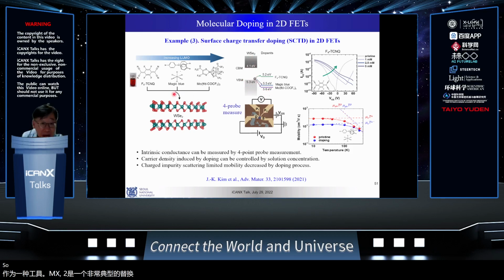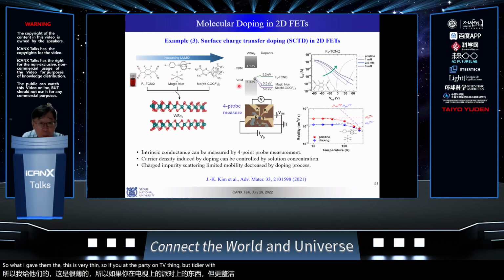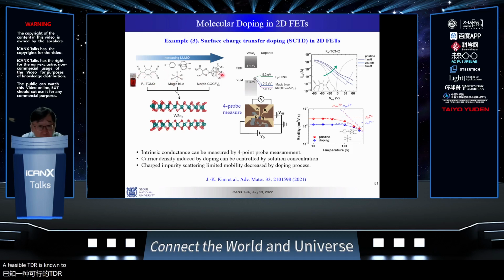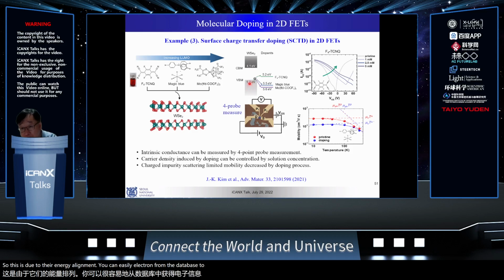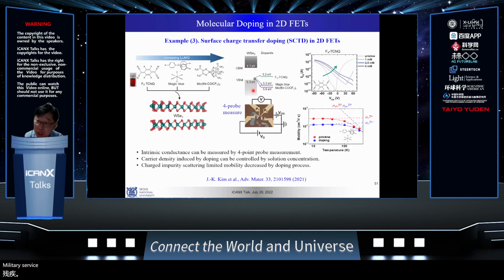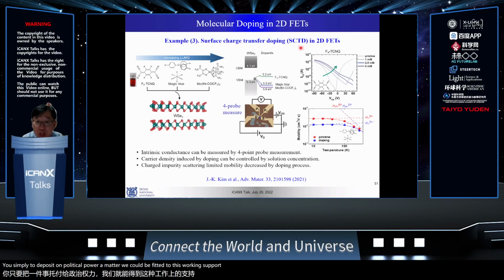So one idea is that this is very thin. If you deposit on the very thin material some molecule which has charge transfer properties, and this molecule is known to withdraw electrons, then it acts as a P-type dopant. This is due to the energy alignment: the electron goes from the WS2 to the molecule. So this can be P-doped at the surface. Simply depositing the molecule on top of the material works. This so-called surface charge transfer doping, SCTD, works because of the very thin 2D nature.